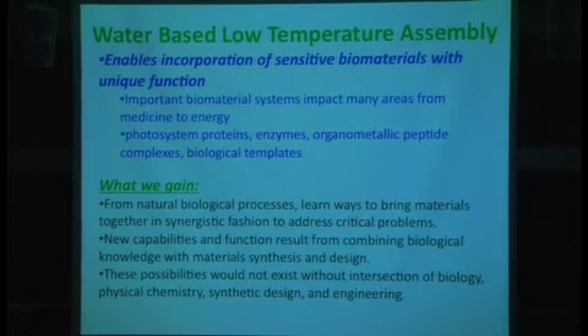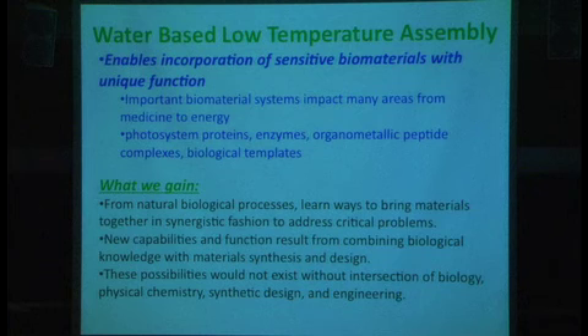So what we've learned from this is that water-based assembly enables us to incorporate very sensitive biomaterials with unique function. We can actually combine different material systems using this electrostatic assembly approach. And it allows us, because it's a water-based system, to bring in biopolymers and biomaterial systems that would normally be fairly sensitive. And there are a range of these things which have applications from energy all the way out to the biological applications that we talked about today.